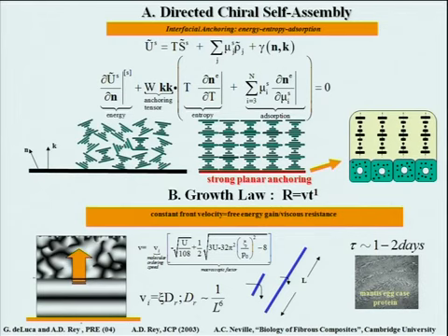So that gives you this expression that tells you that the preferred orientation in any system is a balance between energy, entropy, and adsorption. And you can see here that the orientation at the surface can be manipulated with the chemical potential of a surfactant type, or wax type, or any other chemistry that insects and plants use. And also by temperature. So you can achieve changes in orientation and or determine strong planar orientation at a fixed angle using simple chemistry, which is accessible to the plant or the insect.